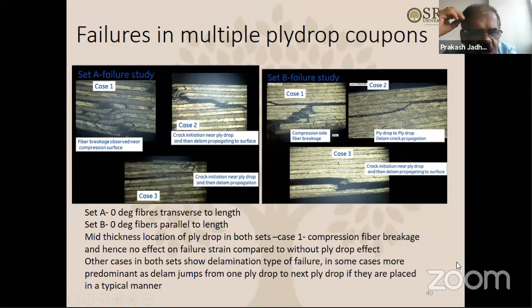And this picture shows how it failed. Case one was the fiber breakage observed near the compression surface. Then case two is the crack initiation near the ply drop and then delamination propagating to the surface. So as you can see, crack initiation happening near the ply drop, and then ply drop to ply drop is jumping actually. As you can see, one ply drop to another ply drop is jumping and going to the surface. In the third case, crack initiation near the ply drop and then delamination propagation here.